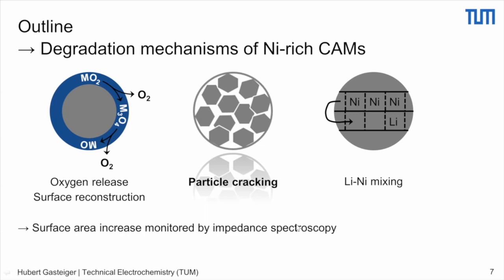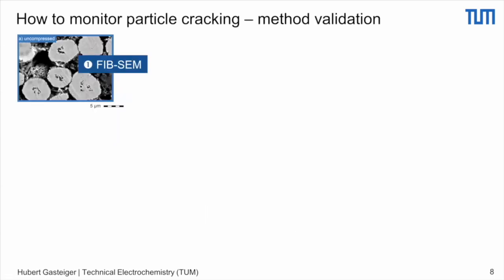which is about particle cracking. And in order to develop an in situ method to follow the particle cracking, we first, of course, had to do some sort of method validation. And the method validation we did was by simply compressing cathode active materials to crack them by mechanical force, right? And so what we know from FIB-SEM measurements is that these NCM materials are pretty dense, have a few occluded volumes, but in general, otherwise they are rather dense.